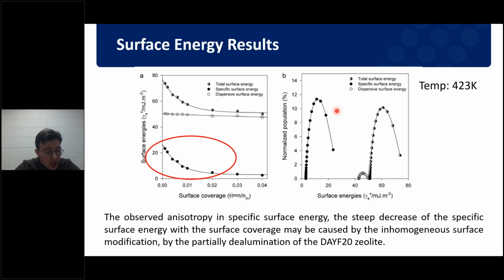So here we can see the dispersive surface energy for this material. And we can see that the dispersive energy is the major component. Therefore, a large contribution to its total surface energy will be that dispersive input rather than its specific. So that is why it would have a very good interaction with our organic molecules, because it has this high dispersive surface energy.